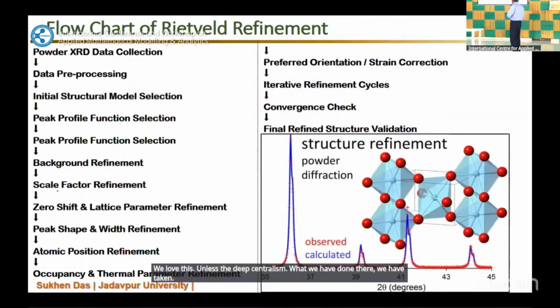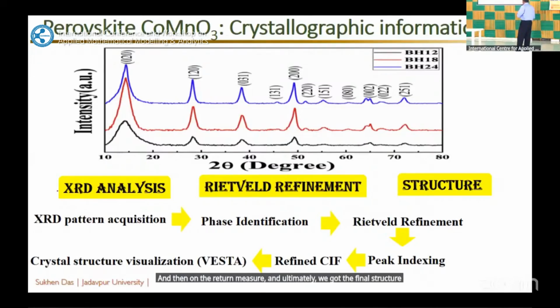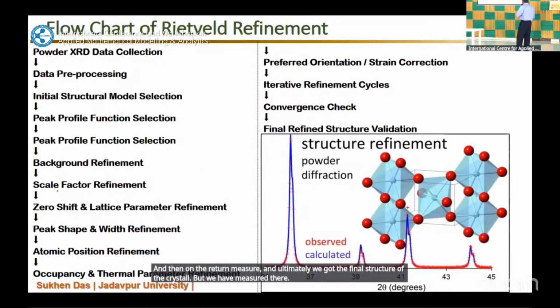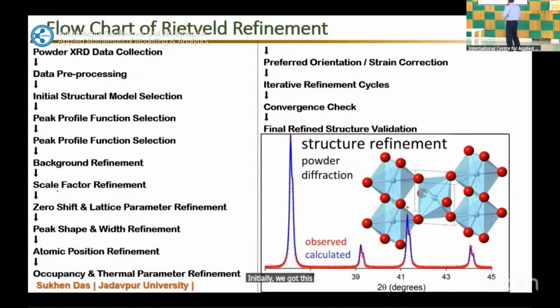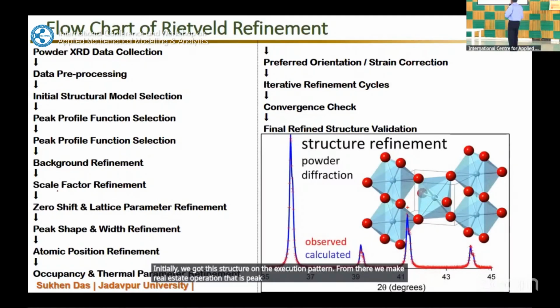What we have done there, we have taken the crystal structure which we got from the X-ray diffraction pattern. From there we identify the phase and then run the Rietveld refinement and ultimately we got the final structure of the crystal. Initially, we got this structure from the X-ray diffraction pattern. From there, we made various types of correction, that is peak profile correction, peak width correction, then the background refinement, scale factor refinement, and all this refinement we have done.